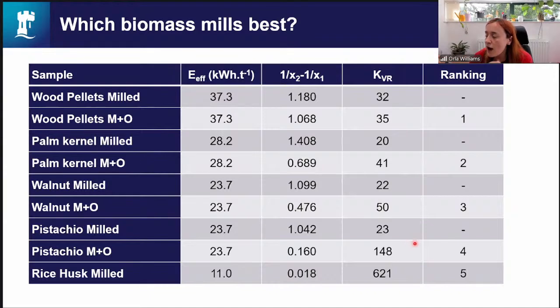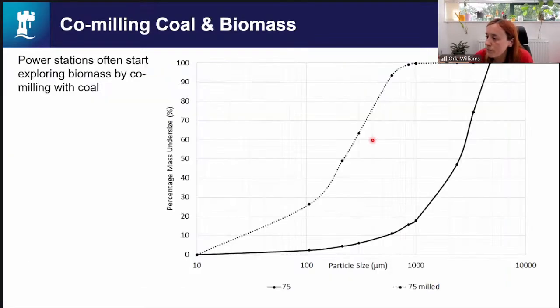So we can use this ranking to assess different materials within that ring and roller mill and see how well they compare against each other. And industry has conducted tests at full scale for the same materials and found that these results correlate. So if it's good in this mill, it will be good at full scale, and if it's not good in this one, it won't be at full scale. This gives industry a metric tool to compare different materials. But obviously we provide the information behind that so they can understand why they're different as well.